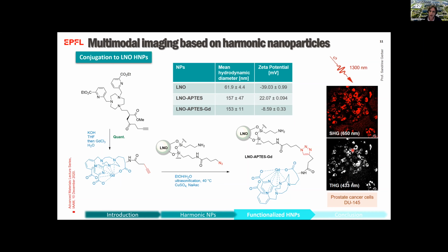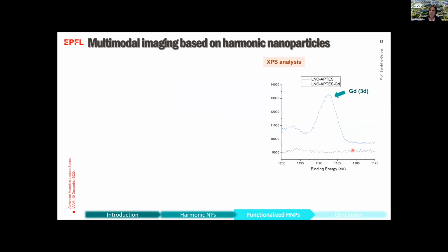Then we went to the analysis of the gadolinium done by XPS, where you can clearly see the signal coming from gadolinium, while the non-functionalized nanoparticles have no emitting signal in XPS.